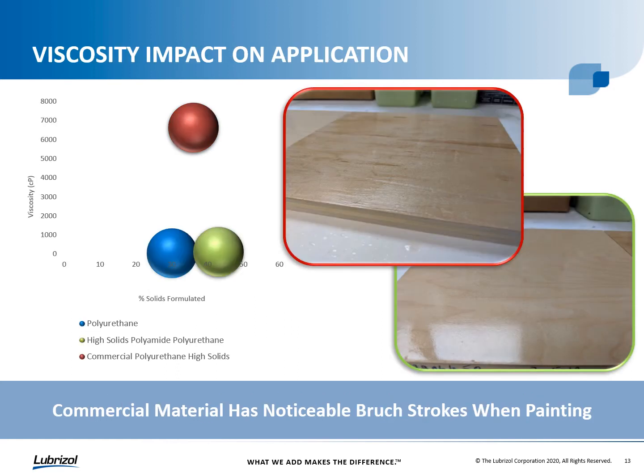So now when we take a look at the impact viscosity has on application, we can see in the top picture that the commercial high solids polyurethane that we bought off the shelf, that was up over 6,000 centipoise in viscosity, that the high viscosity led to some challenges when trying to apply the material. We can see the material had noticeable brush strokes and just a very non-uniform, non-desirable finished appearance on the wood.